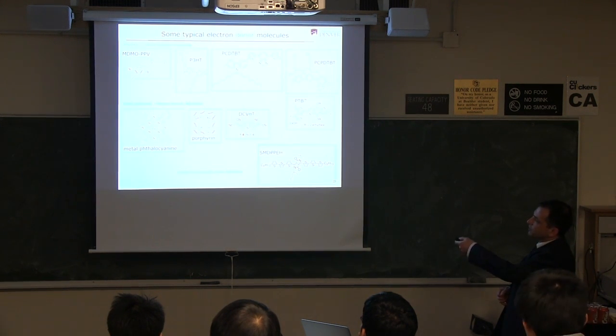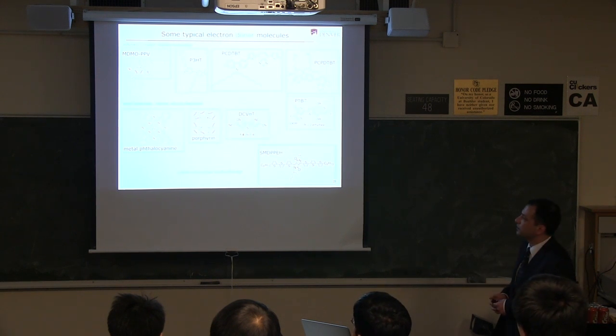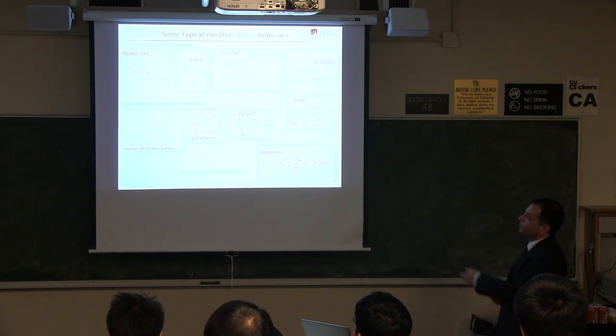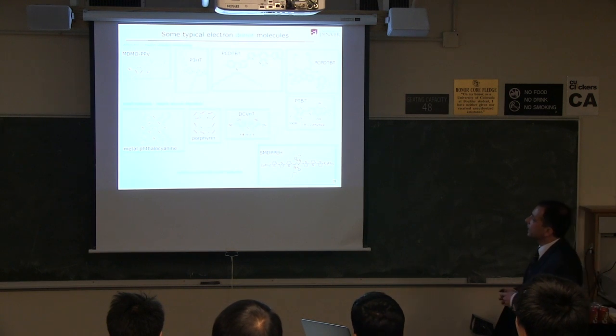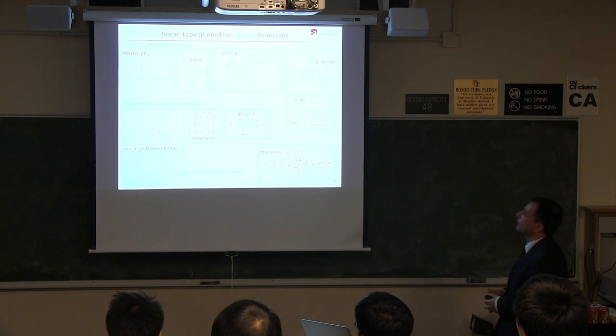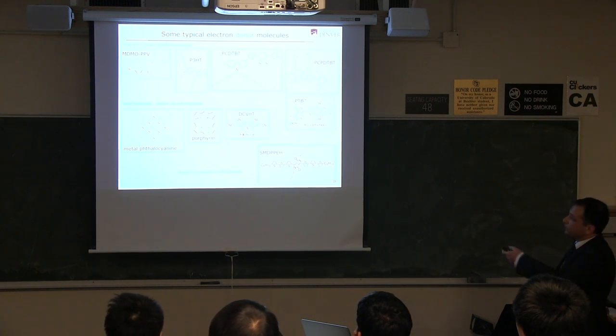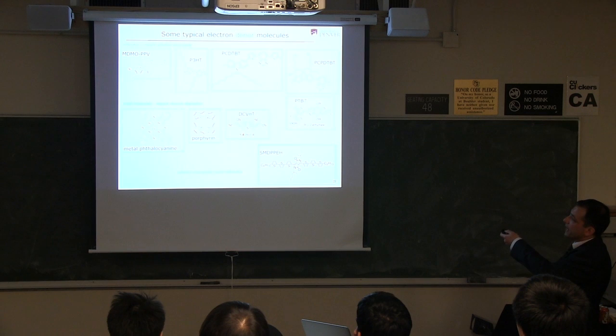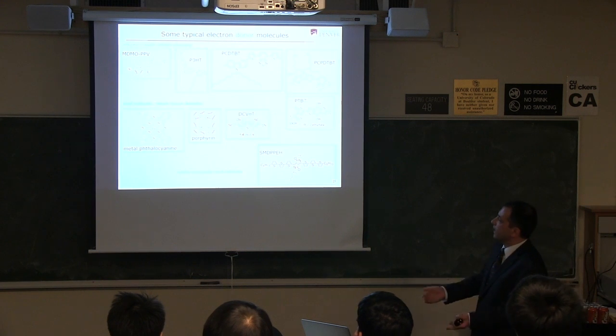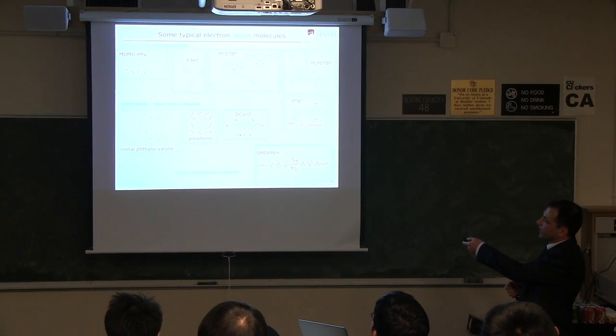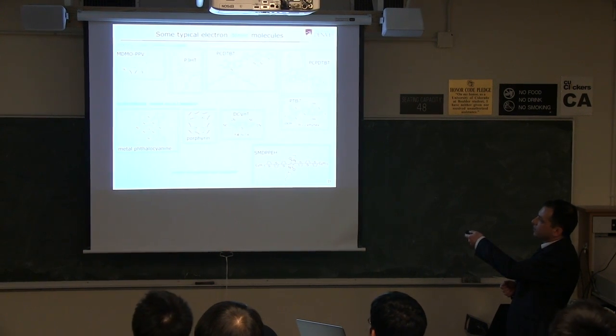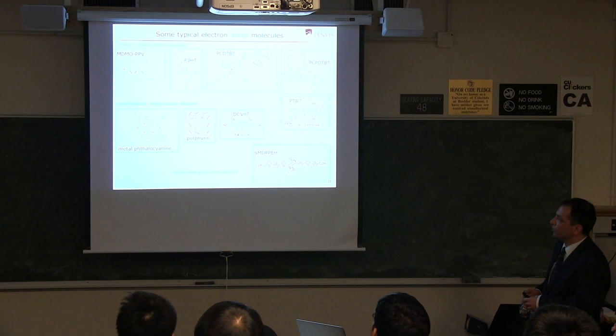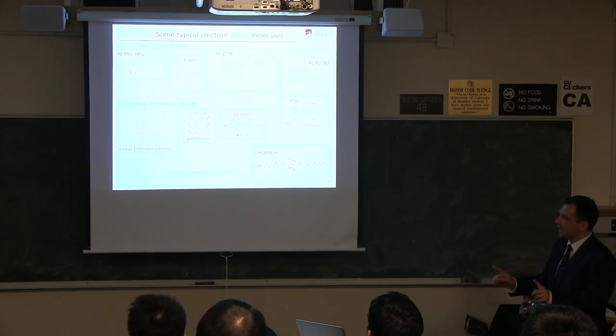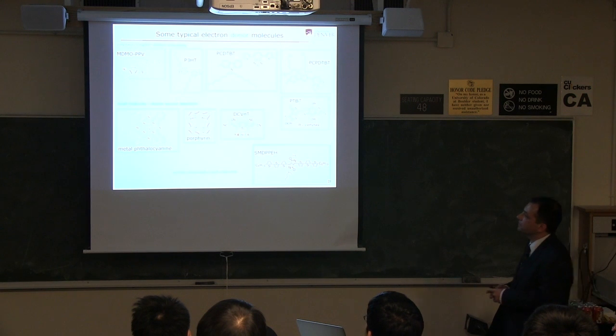So these are early generation materials. The band gap is 2 eV. It's a little high for the solar spectrum. So over time, the band gap has been decreased, first by putting thiophenes in the group. This is poly-3-hexylthiophene, one of the workhorse materials. And then more recently, by putting hetero moieties into the backbone of the polymer, that function to push electrons back and forth along the backbone. That's how you can modulate the optical band gap of the structure. The way these things absorb light is that there are pi electrons delocalized around the ring of the benzene or the thiophene, and they become delocalized along the backbone of the polymer. Those are at the core of the electronic excitations that absorb the photons that come in.